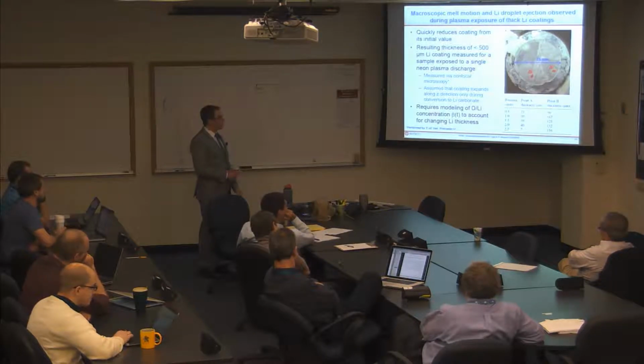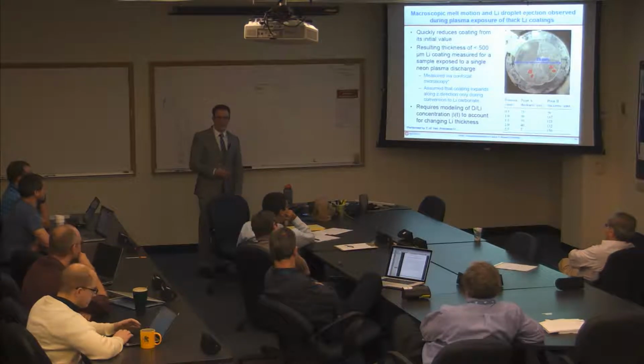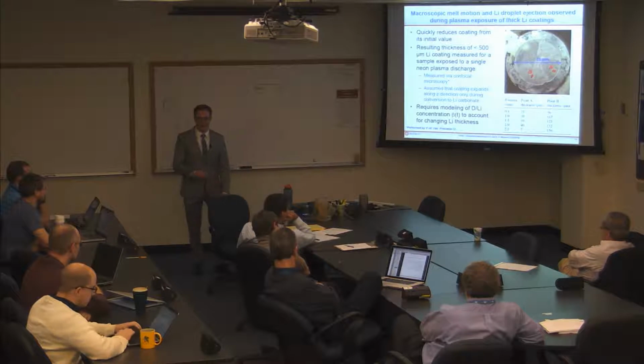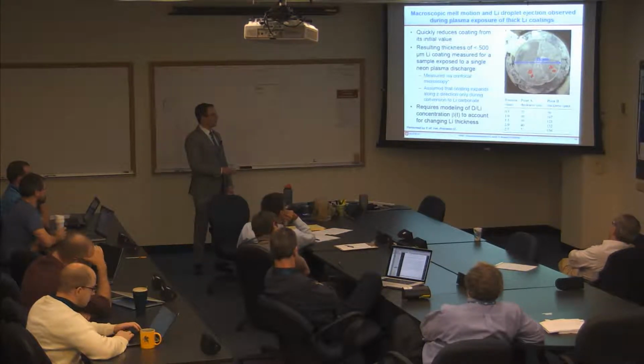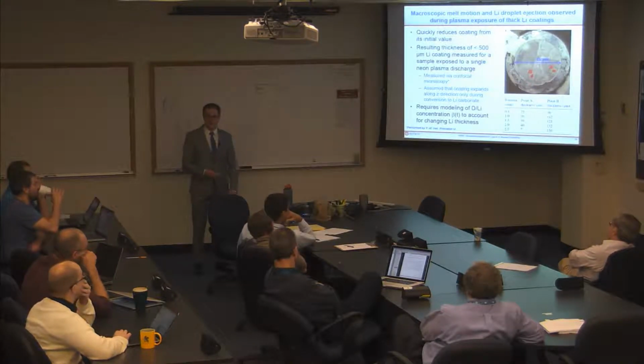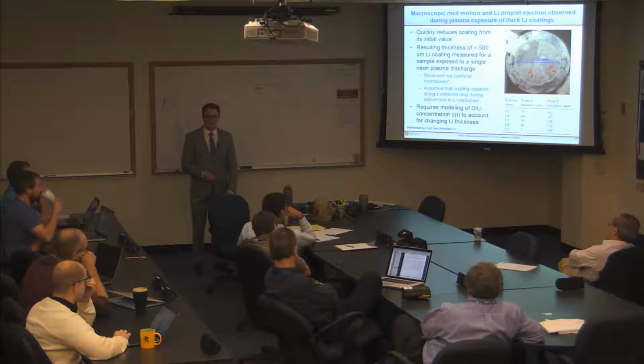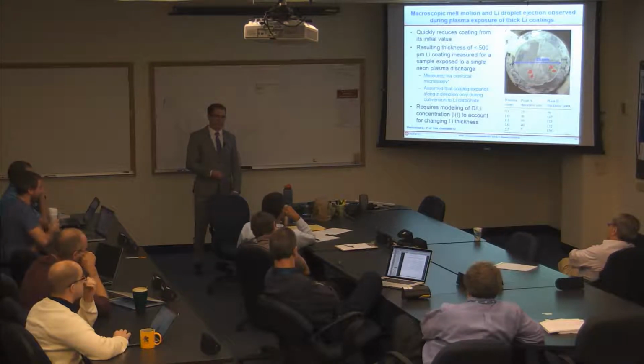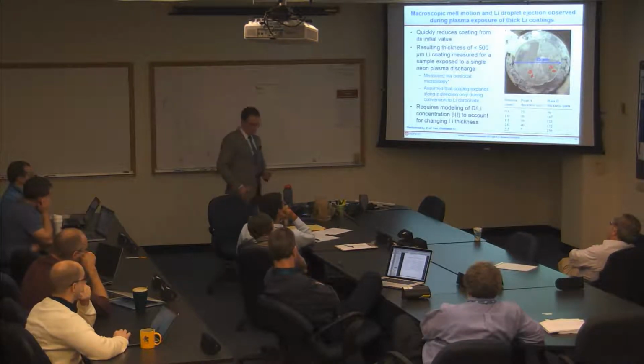so lithium wetting of metal surfaces is kind of complicated, and sometimes it seems to wet some areas well and not hold on well to other areas. And that's why I did a measurement on one of the thicker areas, which is point B, and one of the thinner areas. And so this is still just normal incident field? Yeah, this is normal incident field. What position are you talking? Position millimeters on the left?